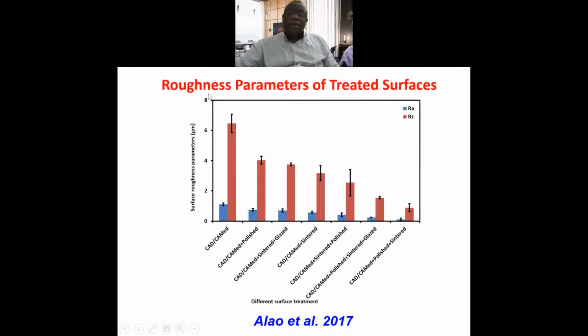So these are the roughness parameters of treated surfaces. You can see the CAD-CAM has the highest average surface roughness and the highest maximum roughness, the difference between the peak and the valley within an evaluation length, that is Rz. So polishing reduces the surface roughness. Then sintering and glazing after polishing, after CAD-CAM milling, also reduce the surface roughness. However, sintering after CAD-CAM reduces it. Then polishing after the sintering process does not significantly reduce the surface roughness.